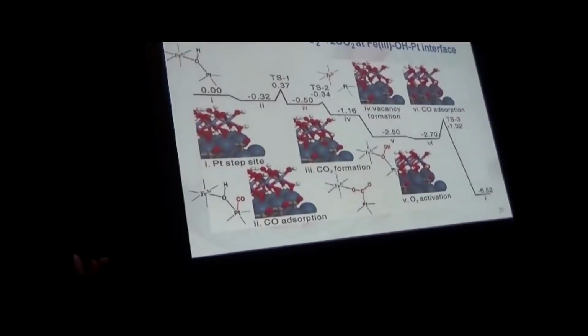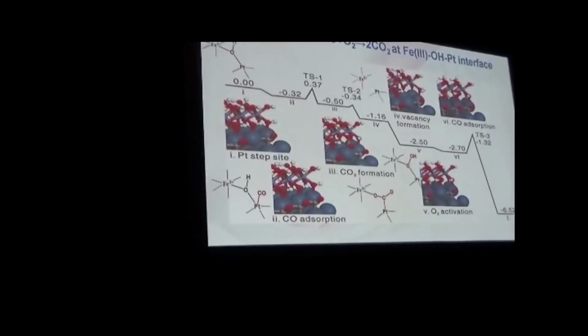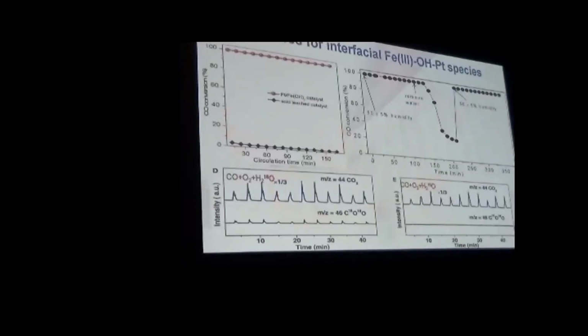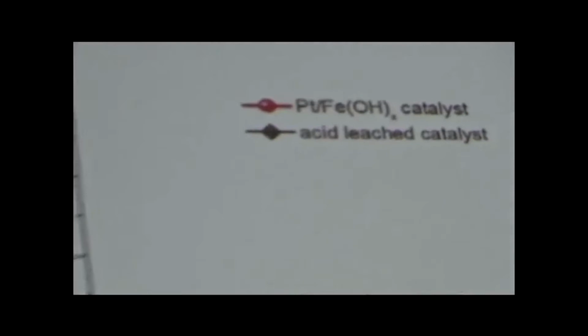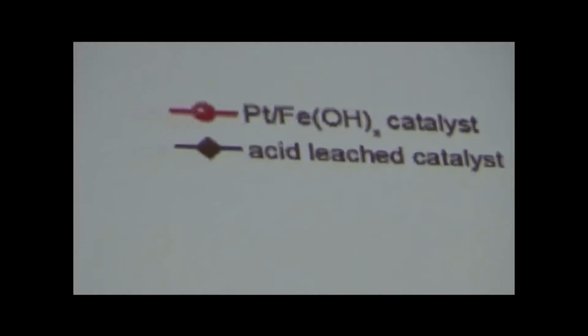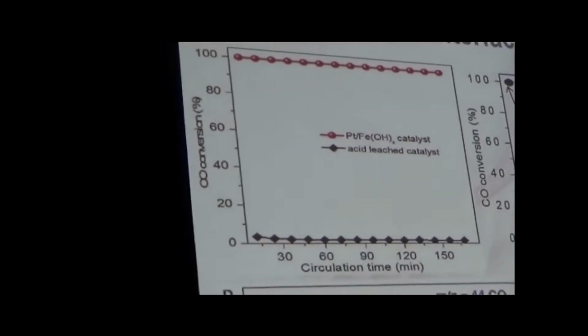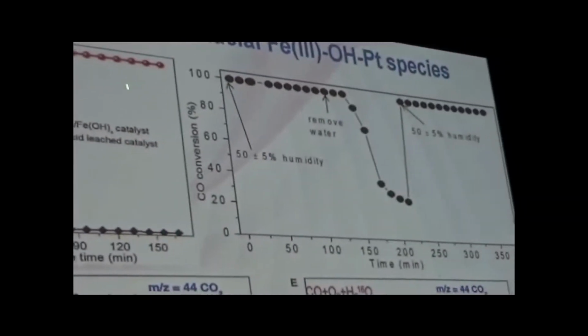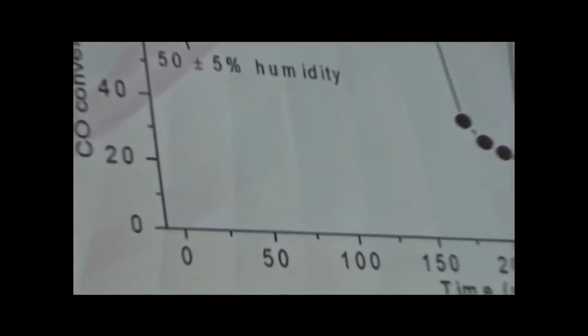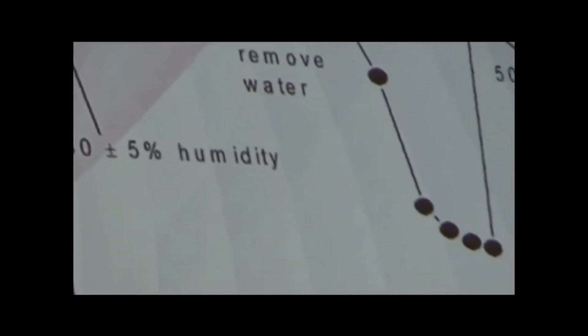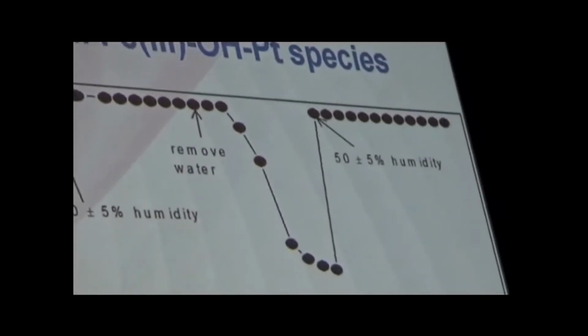How to confirm this mechanism? In this case, we propose the interfacial hydroxyl is very important. Here we have some experimental evidence. The first one: acid treatment can remove the hydroxyl group. Without acid treatment, this catalyst has very good performance. With the acid treatment, you can see that there is no reaction. So the hydroxyl can be removed.